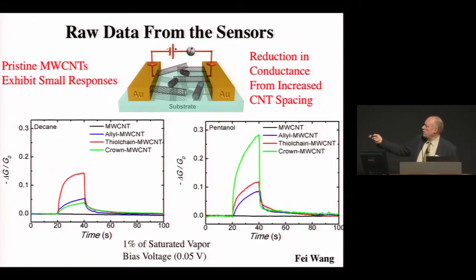Now if we go to pentanol, now we see the one that has the hydrogen bonding characteristics wins in a very big way, because it sequesters the pentanol more effectively into the corona around these nanotubes, and they swell more. And the other thing I want to show you is that the multi-wall nanotubes do not respond at all. So you have to have this functionality to make them respond. And they're also very, very robust in that they always come back to baseline. We anneal the sensors at 130 degrees overnight before we start.